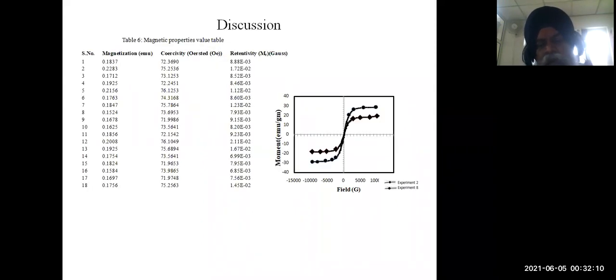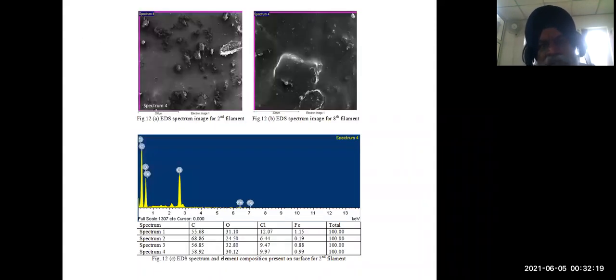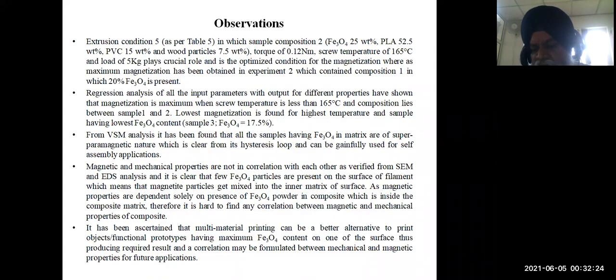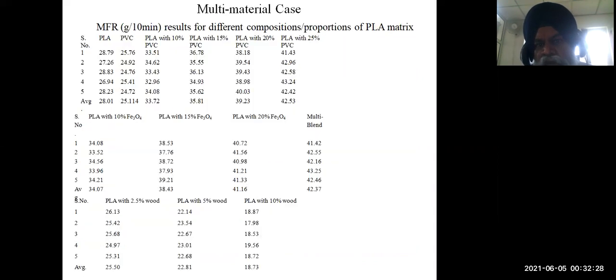We tried to find out how much magnetization, coercivity, and retentivity will be there, and we tried to correlate with some BH curves and some ANOVA analysis, statistical analysis based upon some SEM and EDS analysis. We came up with some optimized setting. What should be the composition of which material in this?